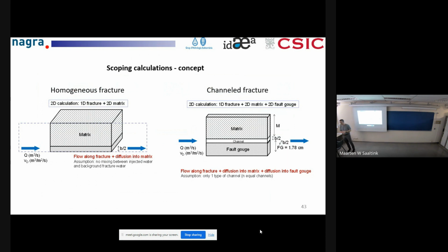In this calculation, the flow here is through the fault gouge, but here it is only through the channel. The fault gouge is very similar to the matrix. It has much higher porosity, higher diffusion coefficient. It is a sort of other matrix, a different matrix. But in terms of flow, that's important for the sorbing tracers later. Flow goes through the fault gouge here, and here flow goes through the channel, because in principle it's the higher permeability part.